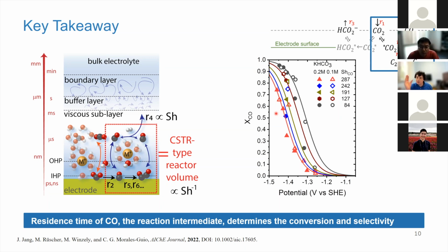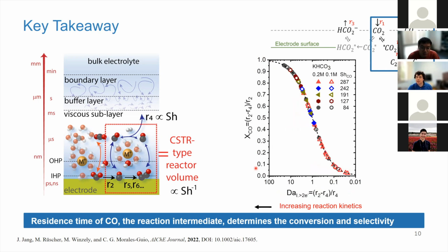But once again, you correct for that tau. So in CO2 electrocatalysis, as you go towards the left, you increase the reaction kinetics. We have done different experiments with different coppers, different copper morphologies. Once you account for the residence time of the reaction intermediate, all these experiments collapse into one line that tells you the relation between the Damköhler number and the conversion of that CO. And I will tell you how that relates to selectivity.